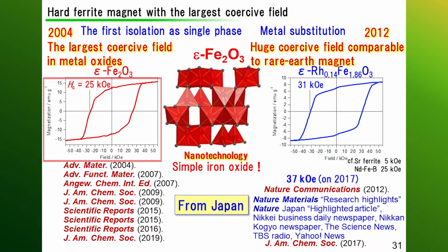The horizontal axis shows the field, vertical axis magnetization. The two curves show horizontal separation, and this is called magnetic hysteresis, with a value of 25 kilo-Ørsted, demonstrating the largest coercive field of all metal oxides.